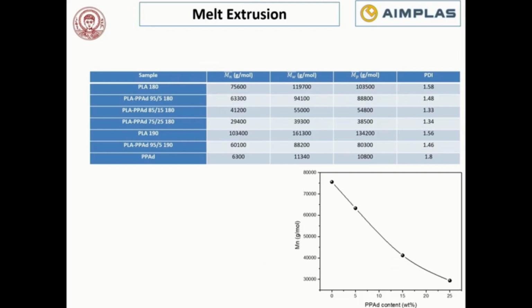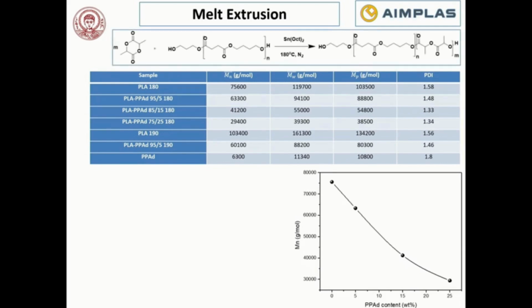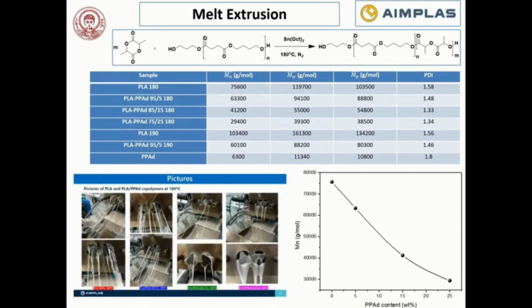And with another partner, AIMPLAS, we applied a new technique to produce some copolymers by using ring opening polymerization of PLA, because PLA, we know very well, is a compostable material, but is not biodegradable. We want to see how to produce biodegradable material, and with this technique, using reactive extrusion, we succeeded to produce high molecular weight polylactide in just 15 minutes. To produce this molecular weight in a laboratory scale apparatus, you need more than 2 hours, and we succeeded to produce it in just 15 minutes.